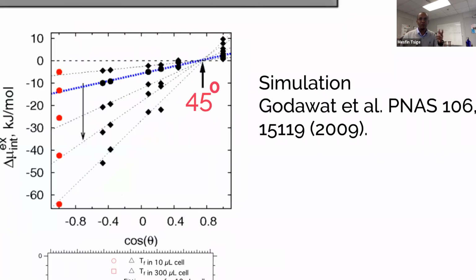With that, a couple of groups from the simulation side, Garde's group from RPI, showed in 2009 that when they calculate what they call the free energy of hydration of a hydrophobic solute near the surface, by how much the free energy changes on the surface compared to bulk water, they see a negative value on hydrophobic surfaces and a positive value on hydrophilic surfaces. This is by varying the size of their solute. And they observed that all of them cross at one particular point, which corresponds to a contact angle of around 45 degrees.